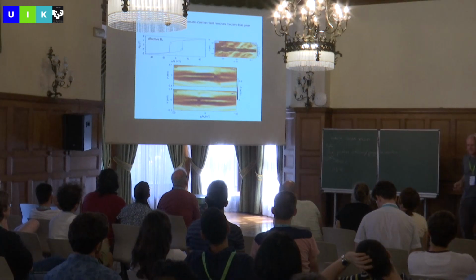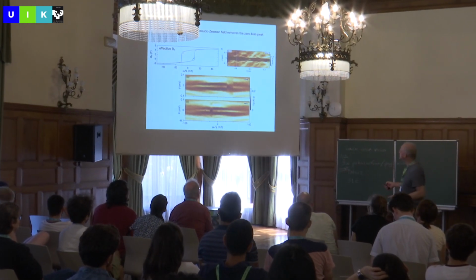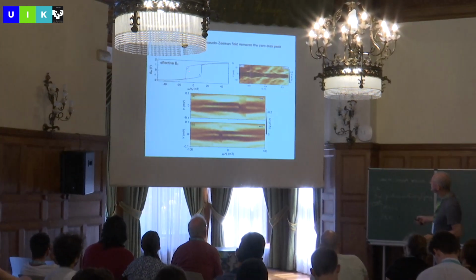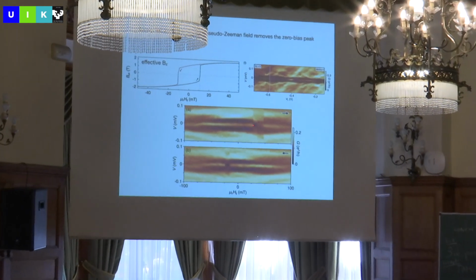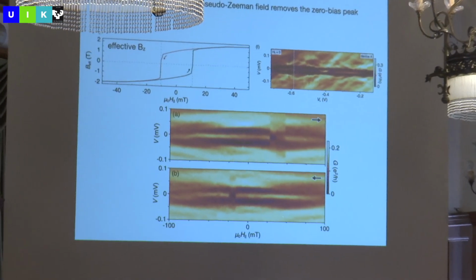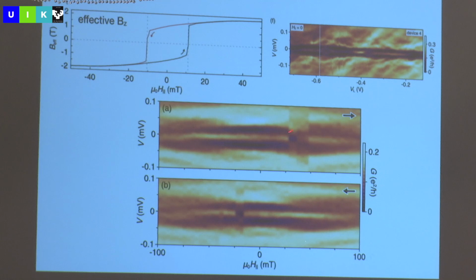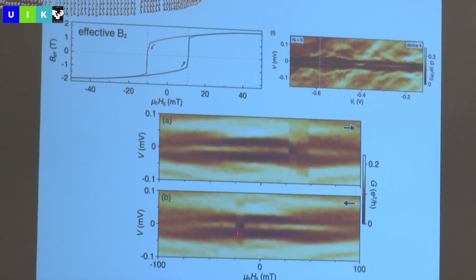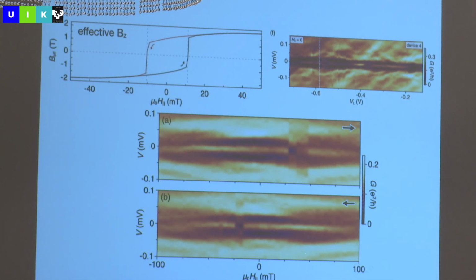Oh, there's one other thing to tell you which is cool, which is when you go back through this coercive field to find the zero of magnetic field, the zero bias peak disappears. Just when you sweep this way, it disappears right at that coercive field. When you go this way, it's just at that coercive field. So you can shut it off, and then it un-zero-bias-peaks the zero bias peak.